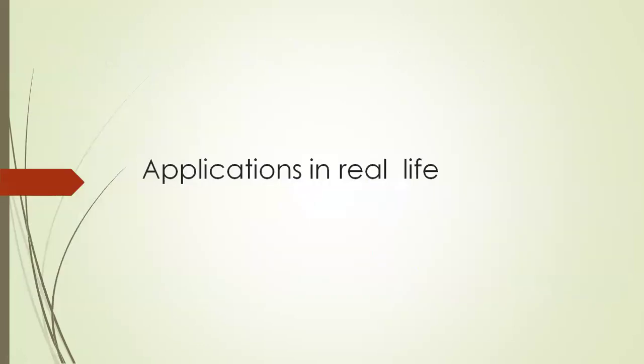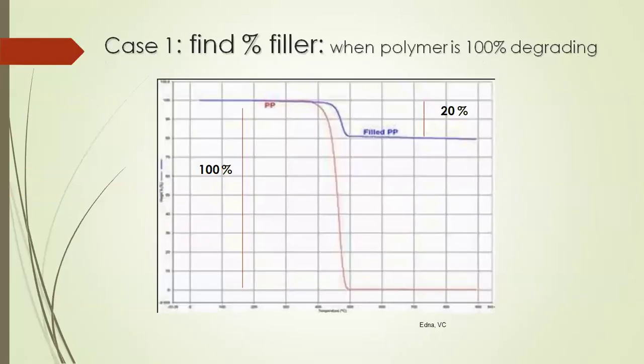So, application of TGA in real life. You don't get only onset of degradation, degradation temperature and percent weight loss in TGA. You can use your TGA to find out the percentage of filler. This is important for research and manufacturing people also, because many times product properties may fail in quality control because of a change in the filler percentage. If a manufacturer makes a small change in filler content, it is going to affect the mechanical properties of your material a lot, but the manufacturer gets a huge benefit in terms of cost, because filler is always cheap. Many times it's cheap.